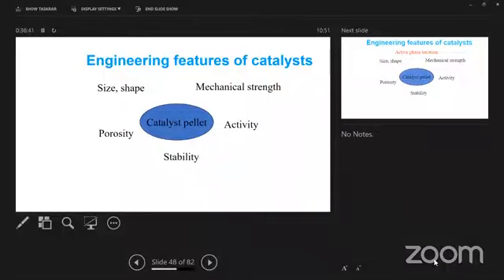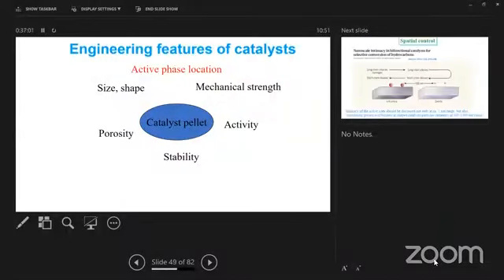In this particular case, what I'm discussing now, we have the acid function, but we also need the metal function. So we make the extrudates, the catalyst pellets. It's important to have active, stable, certain porosity, the mechanical strength, and size and shape. But also it's important where we put the active phase. And the active phase in this case is the metal. Because once again, we have hydrogenation, cyclization, and then hydrogenation once again.